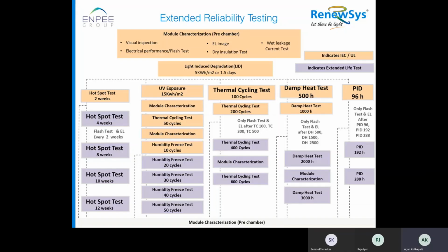The other set of modules will go for UV exposure, 15 kilowatt-hours per square meter, and we do have a UV chamber in our lab. After UV, it goes for thermal cycling, 50 cycles. Again, it goes for humidity freeze for 10 cycles. Here we extend the humidity freeze cycles up to 50, and after every 10 cycles, we check the power loss or the degradation that happened to the module.